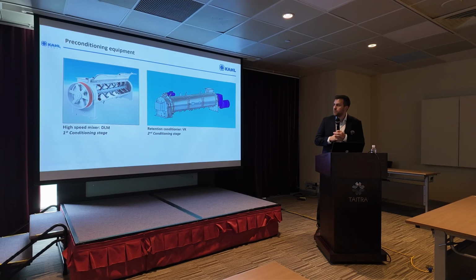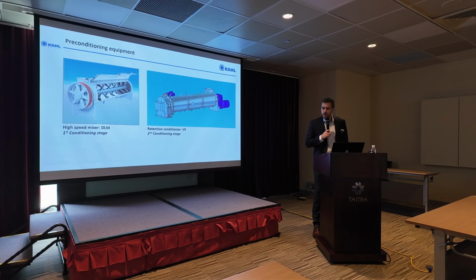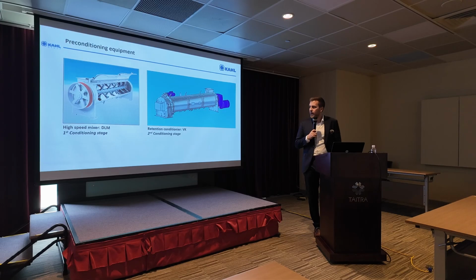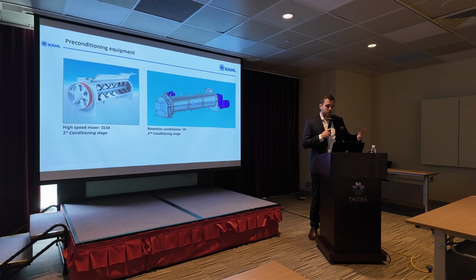This is the setup that we normally use for our plants. We have a high-speed mixer, the so-called DLM. This is the first conditioning step. This is really to kick off the process and start the cooking. Roughly speaking, we will add 2/3 of the steam in this high-speed mixing. It allows the addition of a high amount of liquids and has a short retention time. And it's really intense. You can see we have here really strong paddles that allow a high RPM, and has roughly, I think, 30 seconds retention time.